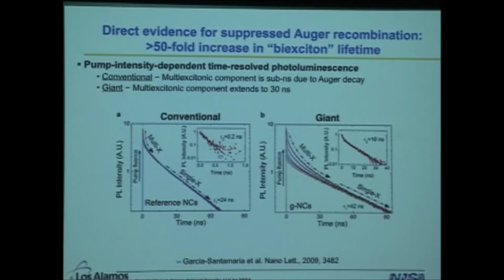And so what we see here on the left are time traces as a function of pump fluence for conventional quantum dots. And you see that standard PL decay from biexciton or multi-exciton states is very, very rapid due to Auger recombination processes, whereas single exciton decay is, of course, much slower. It's not affected by Auger. And so this rapid decay of multi-excitonic states is an indicator that Auger is active.